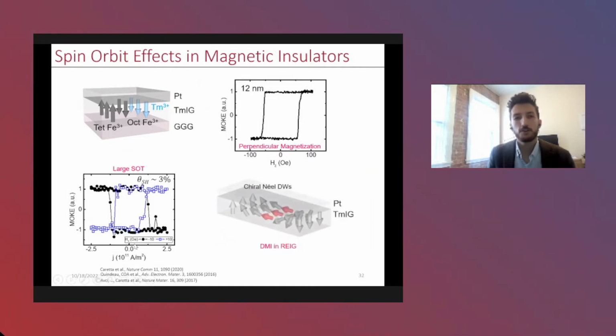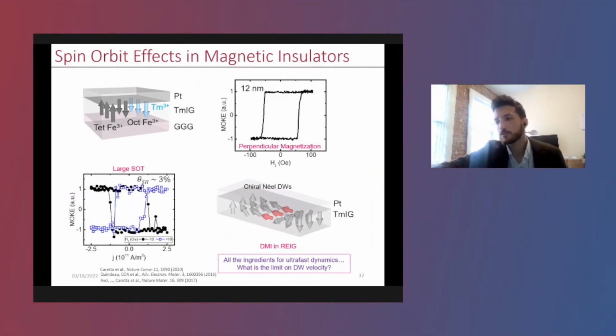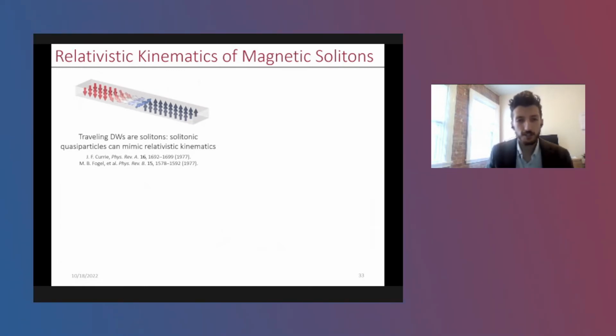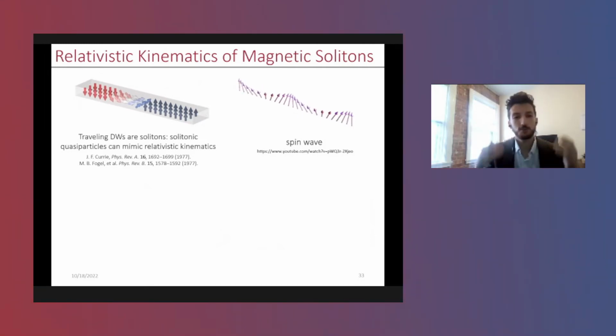And more recently, our group, as well as others, which was described earlier, has discovered things like chiral Néel domain walls and chiral exchange interactions across various interfaces in these material systems as well. So this, combined with the damping and the other tunable properties, really gives us all the ingredients that we need for ultra-fast dynamics in these material systems. So what actually fundamentally limits the velocity of a domain wall? Well, this is actually a solved problem, solved almost 50 years ago in the 70s by a few different groups. I just named a couple papers here, but it turns out that solitonic quasi-particles, such as domain walls, can really mimic relativistic kinematics. And one way to think about this is solitons, or solitary wave packets, are essentially a superposition of spin waves.